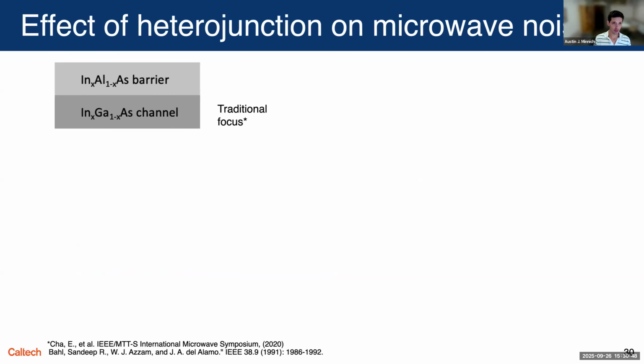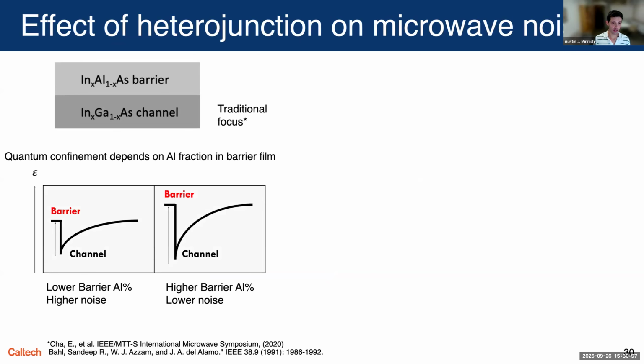One way is to adjust the properties of the heterojunction, but not change those of the channel. And the reason is you want the conducting properties of the channel to not change, but you want to alter the confinement of the electrons in the channel. The way you can do that is actually altering the alloy percentage of aluminum in the barrier. And because a heterojunction requires two parts, if you change the properties of the barrier, you'll actually change the confining potential of electrons in the channel without changing the channel itself. Okay, so that's the idea.